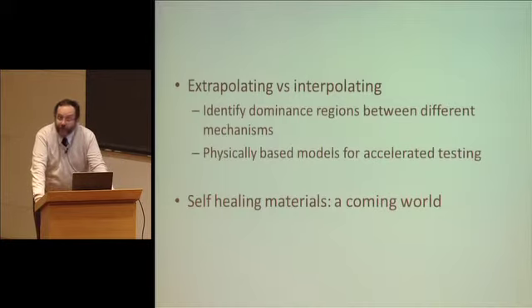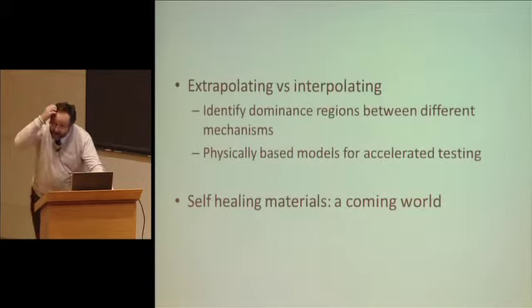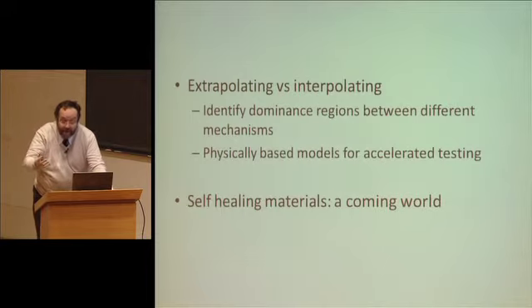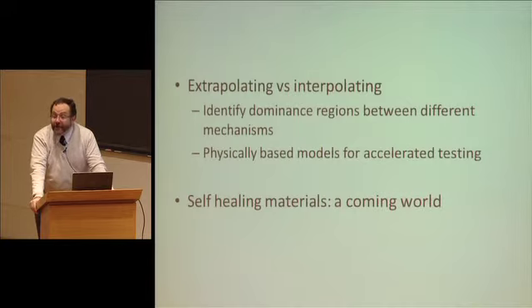What I have tried to show you with these 2 cases, that of creep and that of wear, is basically the rules to allow you to find whether you can extrapolate rather than just interpolate. And the rules that have emerged are rules of identifying fields of dominance, regions of dominance between different mechanisms, and within those, to start with physically based, microscopic models. For creep, microscopic means interaction of dislocations with microstructures, where for wear it's the dynamics and thermics of asperities that are in contact. You need to use those to obtain models which can be extrapolated, while remaining in a class where the dominant mechanism remains.